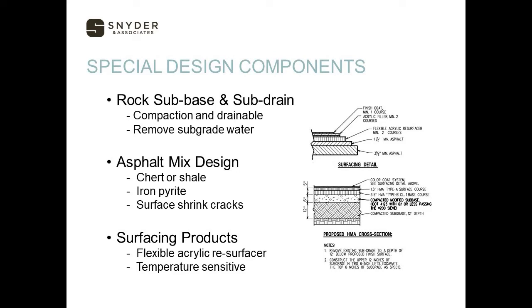For surfacing products, there are three main suppliers we work with: Laykold, PlexiPave, and Sportmaster. All carry very similar products with similar characteristics for temperature sensitivity and timing on putting them down. We want to make sure everything is ready and our surfacing is installed before October 1st. After that, the weather varies too much and we're not getting the nighttime temperatures needed for the top surface paint. The asphalt, after we get it down, needs to be down for 20 days before we start putting our surface product on.